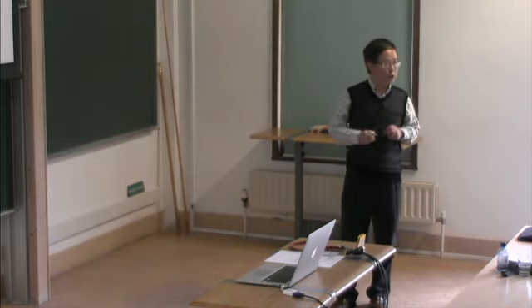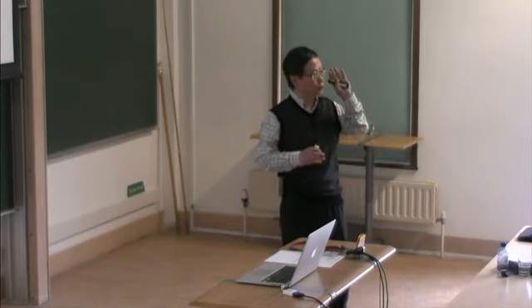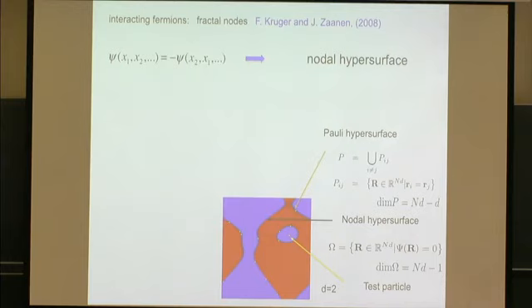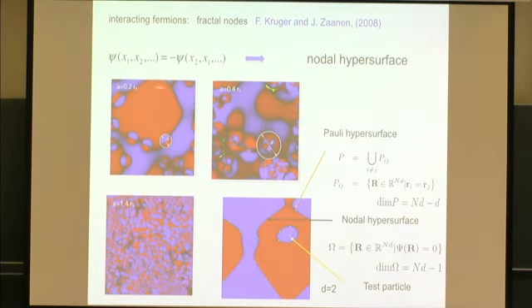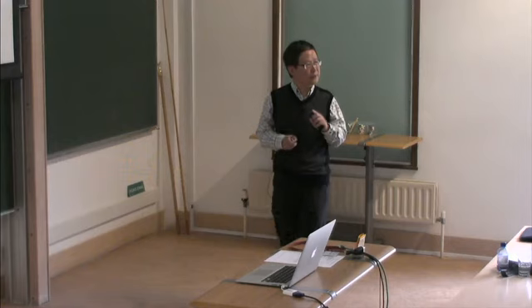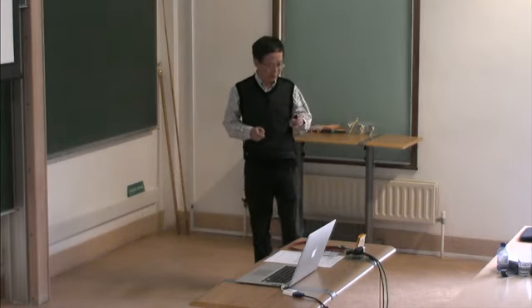And there are many attempts to try to show how you increase interaction to get rid of the Fermi liquid behavior. One interesting approach is to follow the sign change of a wave function, the so-called Pauli hyperspace surface, and then you turn on interaction. Under some approximation, you can show that with increase of interaction, eventually this Pauli surface would have such a fractalized sign change regime that the Fermi energy will be driven to 0. This is an extreme limit where you can get non-Fermi liquid behavior.